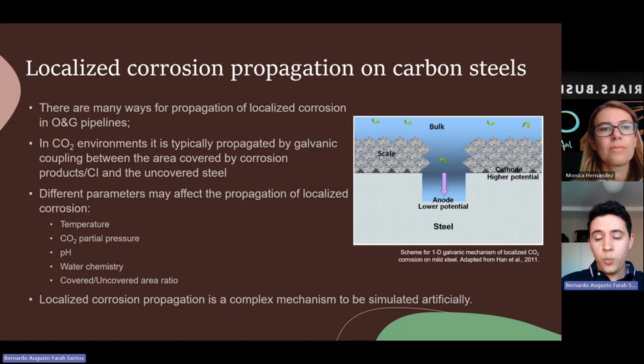And what will happen is that the pit will tend to be consumed, and then the localized corrosion will increase and can cause severe failures. So my study was focused on using corrosion inhibitors to mitigate this galvanic coupling that was established in this local area of the pipeline.